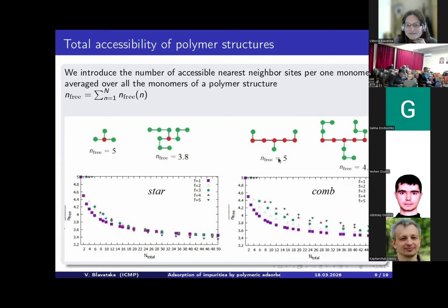And in contrast, when we have a comb structure, since these branches are separated in space, accessibility is much better than for the star-like structure. This is really what we receive here. For the star-like structure, the number of branches starts from 1, where 1 is just a single linear polymer chain, and grows to 5. And for the comb structure, again, 1 corresponds to a simple linear polymer chain, and the number of grafted chains grows from 1 to 5. So we can see how much more efficient the comb structure is compared with the star-like one.